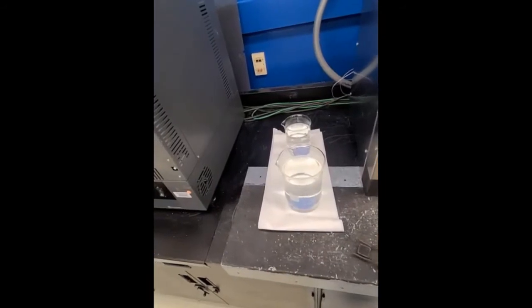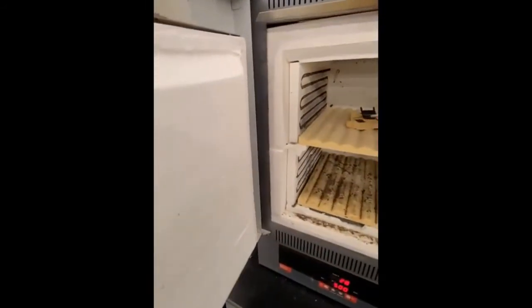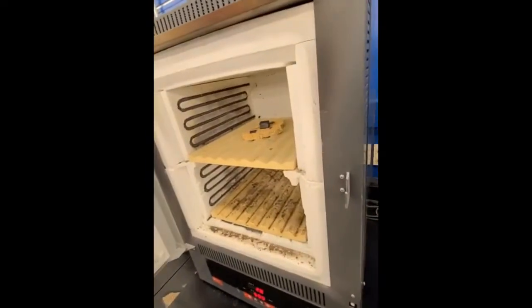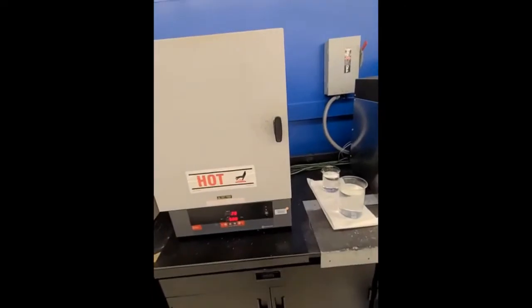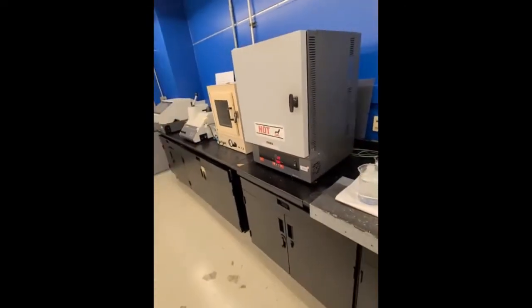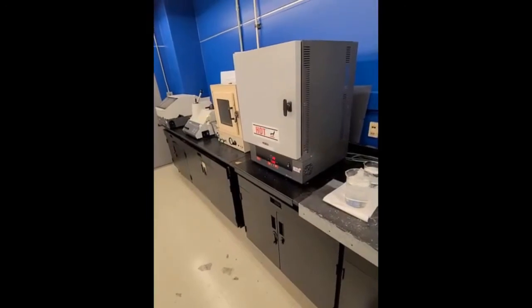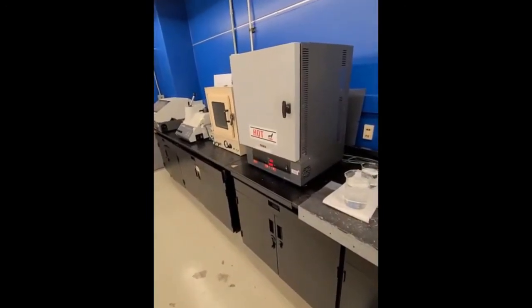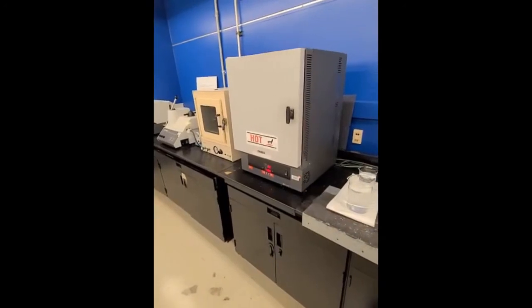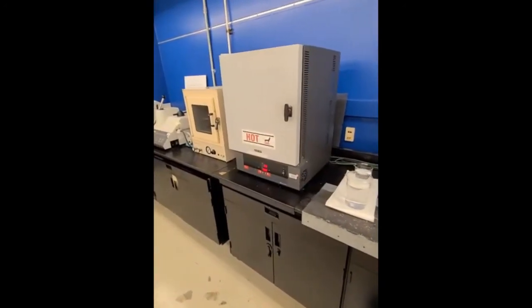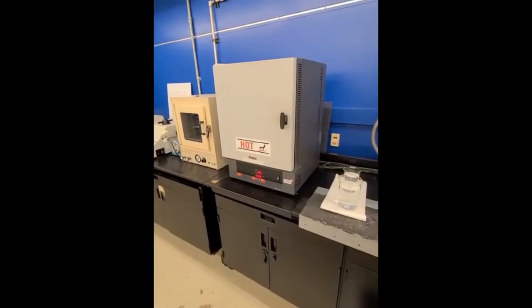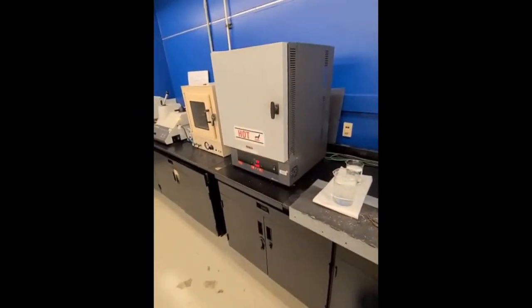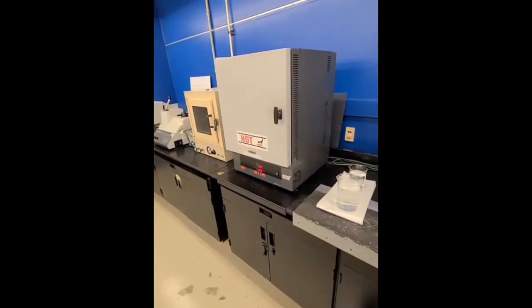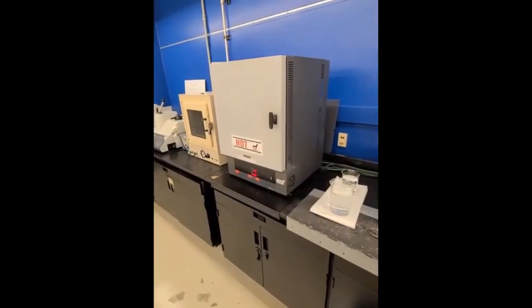I have one of the 2 martensite samples from yesterday. Gonna put it in the middle. So these samples, so that I can tell them apart, I went through and marked them 1, 2, and 3, so I know which is which. Sample 1 is our quenched martensite. Sample 2 will be our tempered martensite, and sample 3 was our pearlite sample. All right, so we'll let this ramp up, and I'll come back after 6 hours and after we've given this the tempering treatment that we're targeting. And we'll quench it down and we'll have our 3 main sample sets.